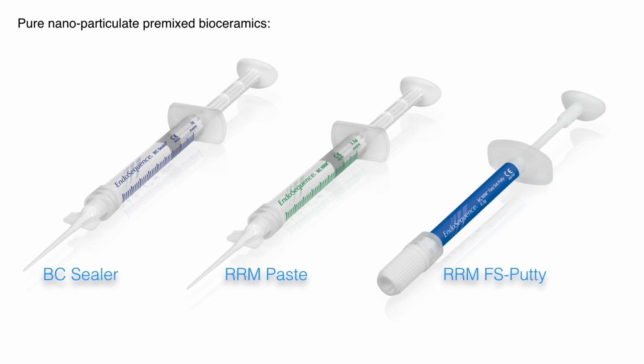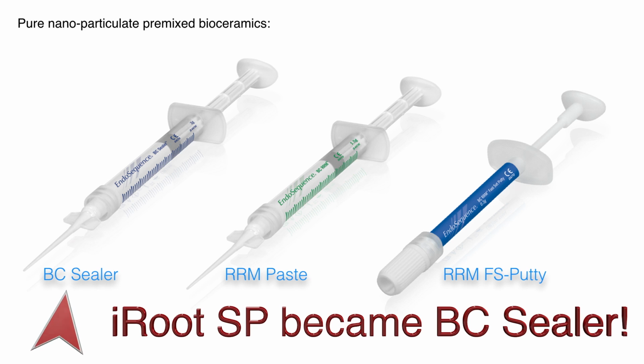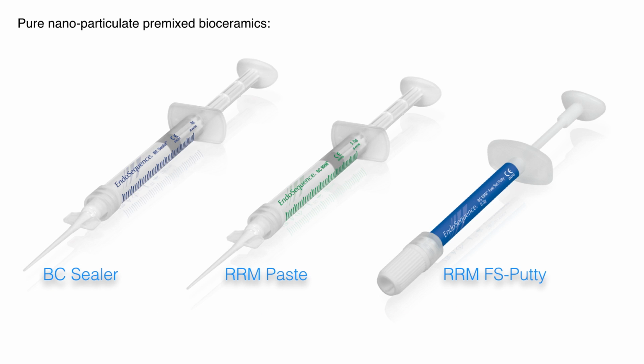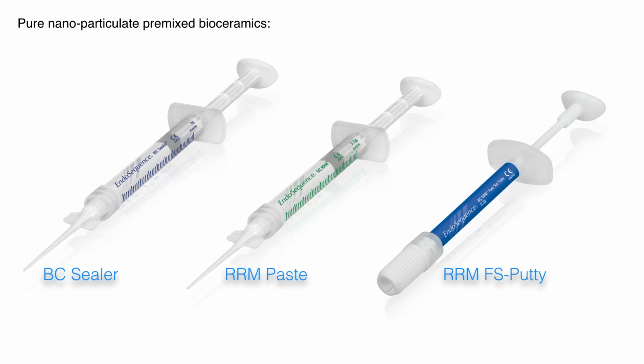And the first one of those was iRoot SP, which was developed with the sub-micron particle sizes that allowed, and also came in a pre-mixed format. So all you basically had to do is use it, as the material was the purest form of a nanoparticulate that was designed from the ground up to work for endodontics as opposed to Portland cement. So basically what ended up happening is that this material became very quickly a replacement for the modern types of sealers that we use for obturation.